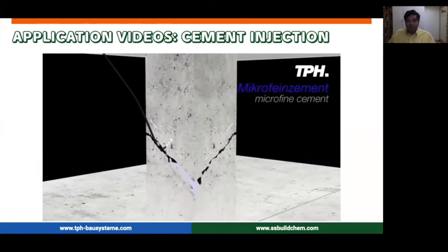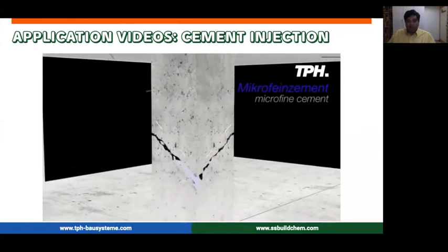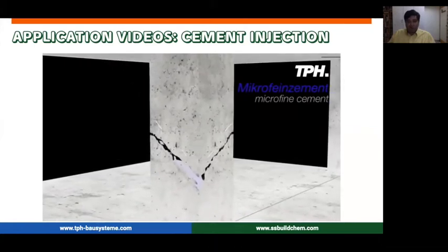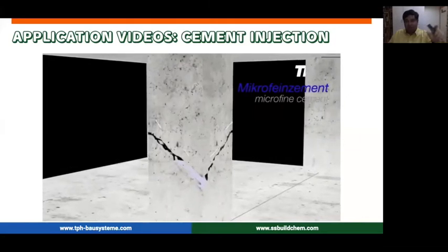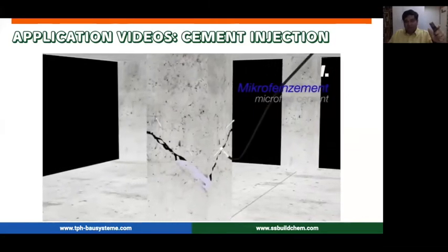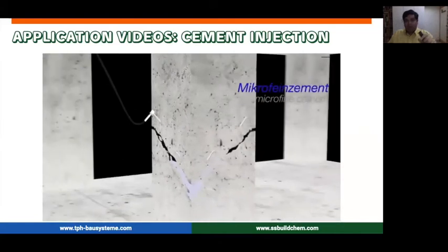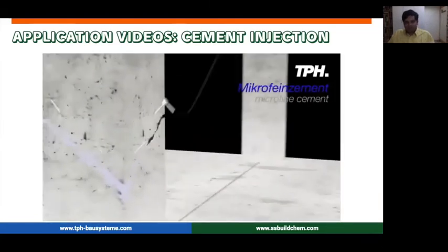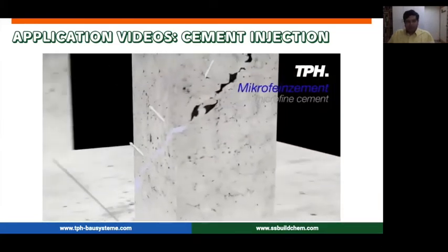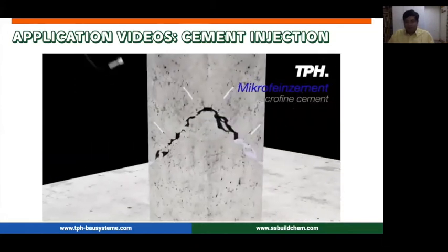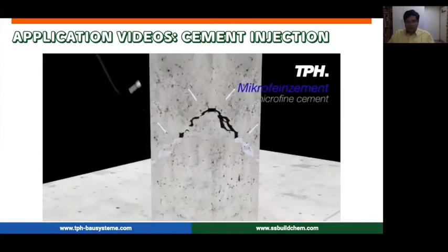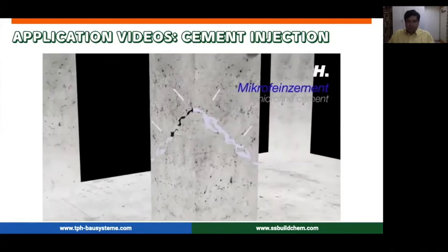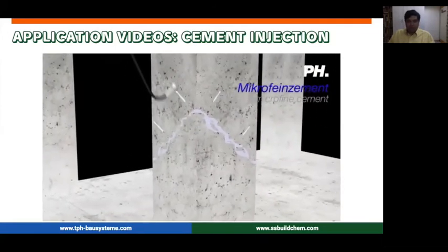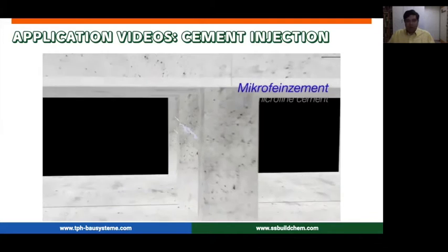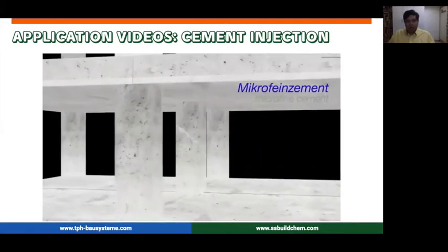This material should be capable of filling in those voids pretty easily, which is why I showed you that graphic on how to select the materials. Your material selection depends on your crack width. Based on that, again, cement and RCC are the most compatible materials. So you can use it for most typical RCC structures where you don't need very high strengths to be transferred. So this is one option of doing it.